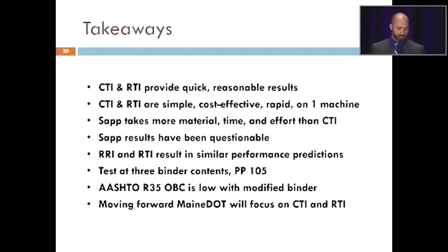So, some takeaways. I don't know why I'm doing on time, but it's at the end now. The ideal CT and the ideal RT provide quick, reasonable results. They make sense. They fit what we see in the field. They're simple, cost-effective, rapid tests, and they're performed on one relatively inexpensive machine that most contractors, most agencies already have, a load frame.